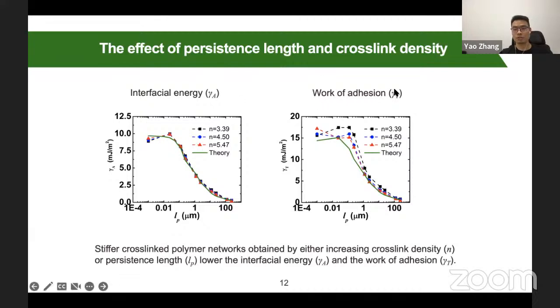How about this work of adhesion, gamma T? The work of adhesion is the work you have done by the force to detach your network from the surface. If you look at the interfacial energy, as your persistence length decreases, you can see that this interfacial energy will reach a plateau when the persistence length reaches about 50 nanometer. If you look at the right figure, it shows the work of adhesion as a function of the fiber persistence length. The same trend happened.